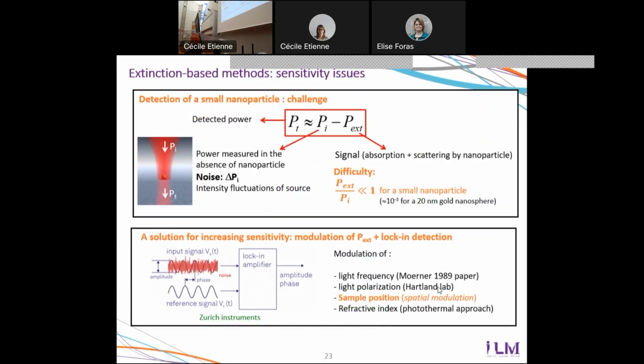It is to illuminate a sample with a very strongly focused laser beam and to detect the attenuation of the beam when a nanoparticle is present in the beam. Because when there is a nanoparticle, it will absorb and scatter light, so less light will be transmitted through the sample. So one wants to detect this attenuation. The problem is that this attenuation can be quite small because the light beam is concentrated on a few hundreds of nanometers. And if the particle is much smaller, the attenuation will be a tiny fraction of the incident beam, a relative attenuation of much, much less than 1.